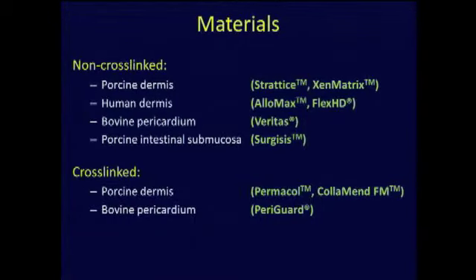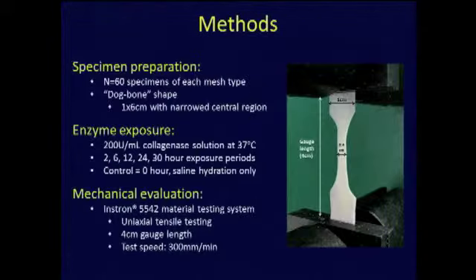We looked at several different commercially available products, both from animal and human sources. We broke these out into non-cross-link and cross-link materials, so that we can actually compare the differences between the processing that occurs in decellularization and sterilization in these cross-linked grafts. One of the difficulties with this, however, is that the cross-linking that is performed is done differently from material to material, so the actual cross-linking process may alter the effect.